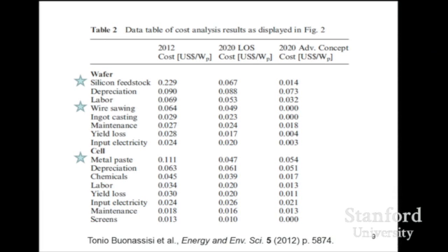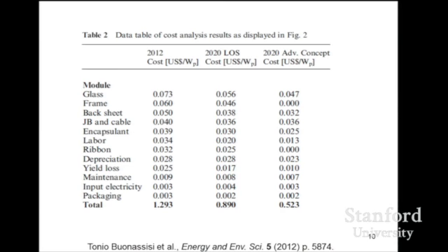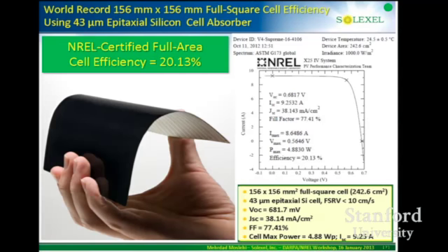Interestingly, another one that jumps out is the silver paste. And if you can find a way to use less paste or use a metal that's not as expensive as silver, there are opportunities for big improvements there. So just to show you that people are working hard on this, a company, Solexel, that's nearby and affiliated with several professors at Stanford, including Krishna Saraswat. They're making great progress in getting the wafers thinner. And here they grow the silicon and then they lift it off of the wafer and they can reuse the wafer. And here you've got a 43 micron cell.